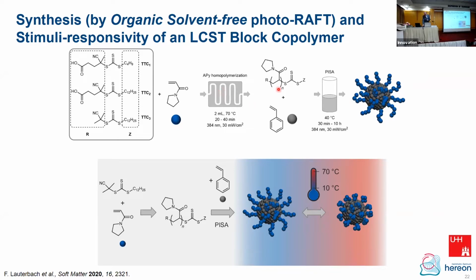He gets a homopolymer of this PAPy without water, and then he puts that into a water suspension of styrene droplets and does the photopolymerization in terms of the PISA process, and generates these wonderful micelles with just water as a solvent, if at all. Because the first work was in bulk and the second was in a water emulsion.